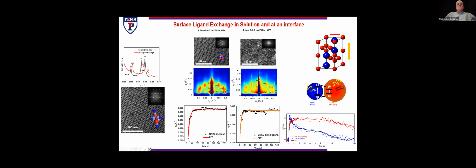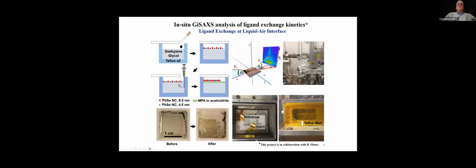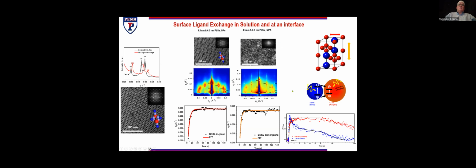And so I wanted to mention some experiments that we actually did carry out at Argonne with the assistance of some of the great teams at your site. And so in this case, we were looking at this exchange process, which is critical to activating the electronic transport in these films. But one of the challenges is to be able to actually watch or understand the kinetic processes as well as the mechanical response as the spacings between these particles is modified. And so in this particular experiment, we were able to do an in situ grazing incidence X-ray experiment in which we introduced a new competitive ligand below the layer of the assembled quantum dot films. This happens to be a 2-component quantum dot film. We'll talk more about that a little later.